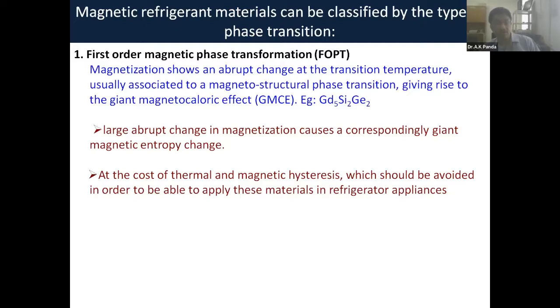Sometimes in papers they call it GMCE. This has been observed typically in gadolinium, silicon, germanium type alloys, where, when you apply a magnetic field, there is a change in the vicinity of the magnetic transition temperature and structurally different phases. Now what happens is you are applying a magnetic field, there is a magnetic transition, something like para to ferro, or in some cases ferro to para, and so on. But in this case, this is reinforced with a structural phase change also.